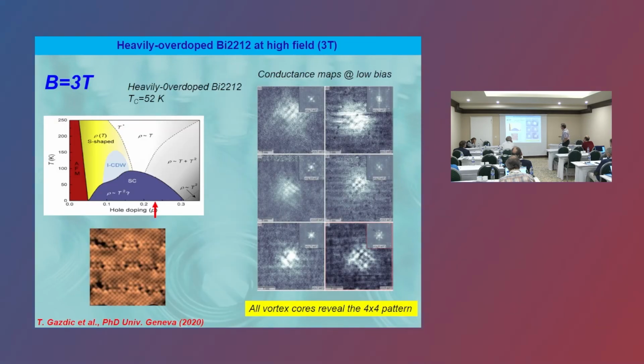And so we first started measurements at 3 Tesla. And the vortices, 3 different vortices shown here, or 6, sorry, all show that kind of conductance modulation, which I reported before, and which were in some cases related to the charge density wave state of the compound, depending on the doping, or quasiparticle interference. But we are now here on the very overdoped side of the phase diagram, so it's likely not possible to link this modulation to the charge density wave.